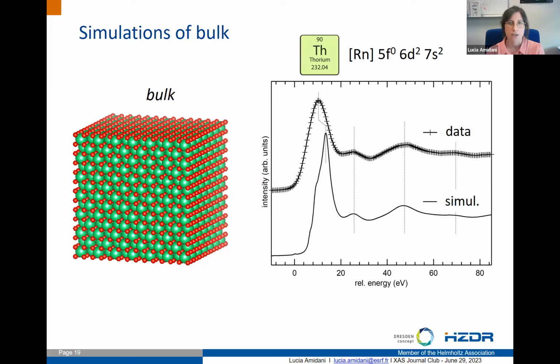The first starting point for calculation is to have something that reproduces the bulk nicely, of course. So I'm using FDMNES, within the DFT approach, which is justified not only because it's the L3 edge, but also because thorium in the 4+ state, and generally thorium, doesn't have F electrons. So I'm in an actinide which has the 5F shell empty. So I'm on the safe side.